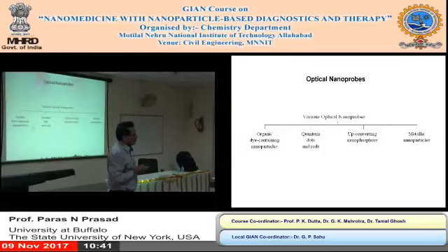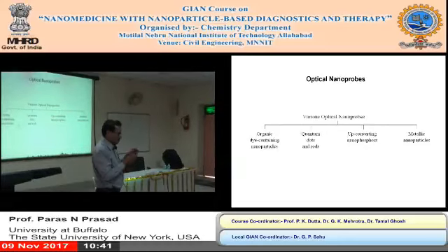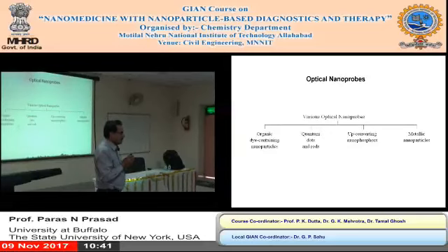However, most dyes have this property that if you load them in high concentration, because you want to make them brighter and more emissive, their emission is quenched. That's called concentration quenching. At higher concentration, when the dyes come together, they decide not to emit but go as heat. So concentration quenching, you want to avoid that. So what do you do then?